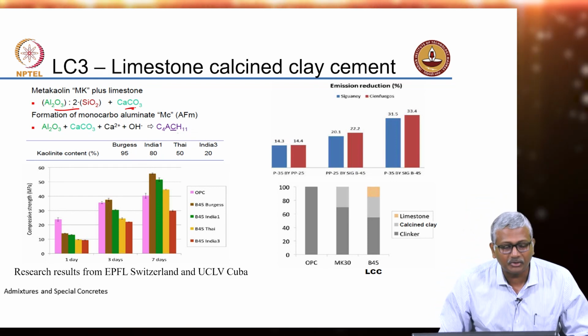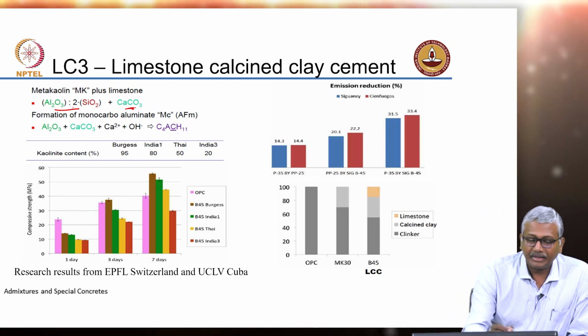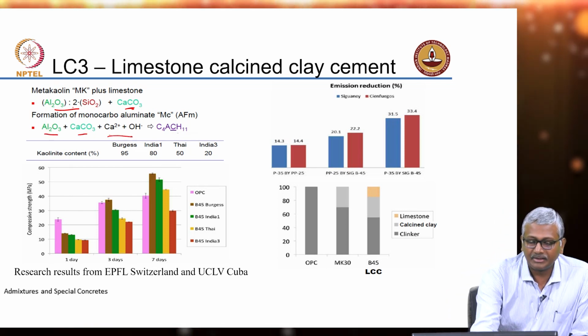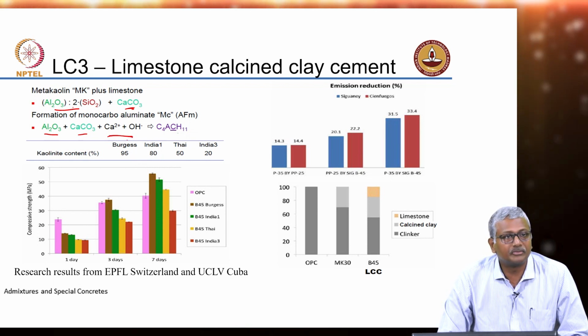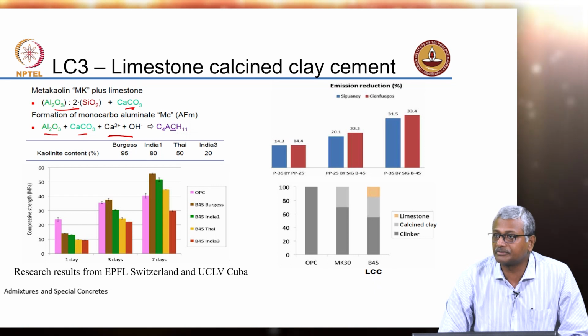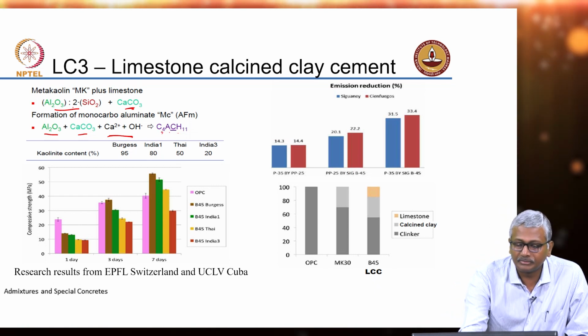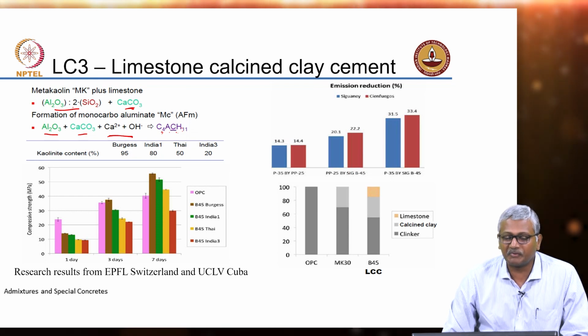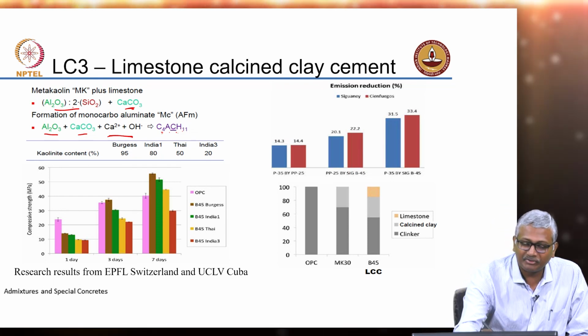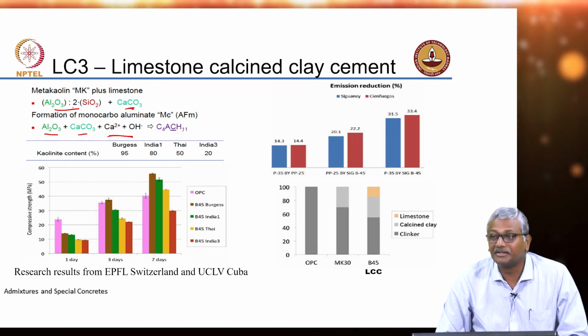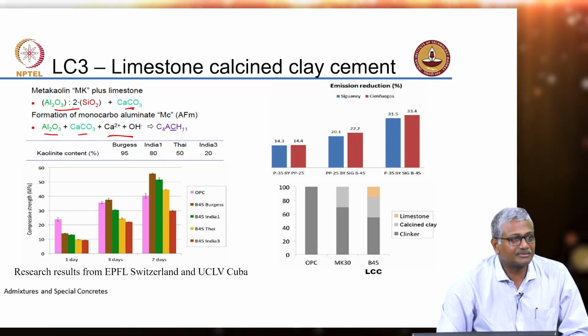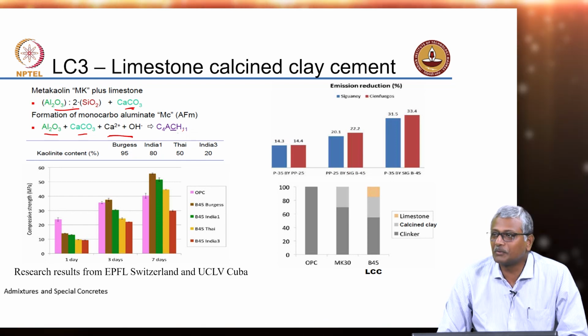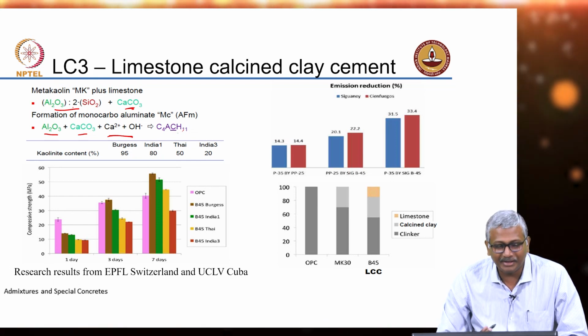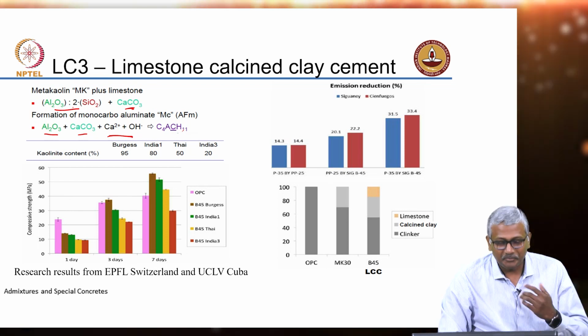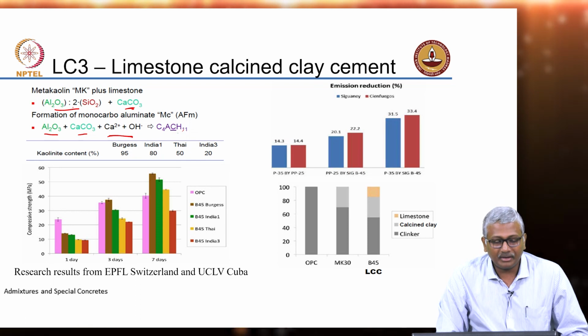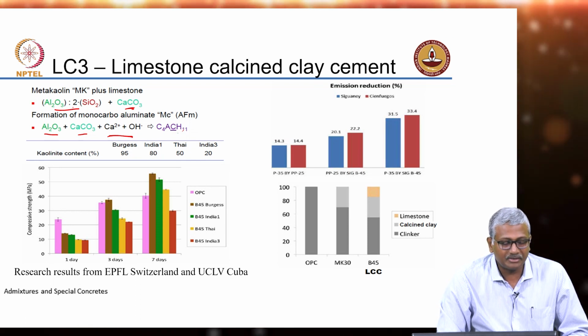Anyway, coming back to the fact that monocarbonate formation involves alumina and calcite along with lime generated by cement hydration to form this monocarbonate structure. So, calcium, alumino, carbonate, hydrate. Now, of course, between calcium and carbon, you can see that cement chemists do some cheating and put a line under the carbon to say that it is not calcium but carbon. If you take this equation to a real chemist, they will throw you out of the room saying, what are you talking about?